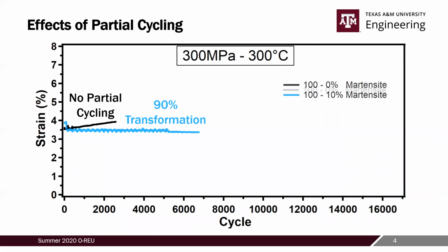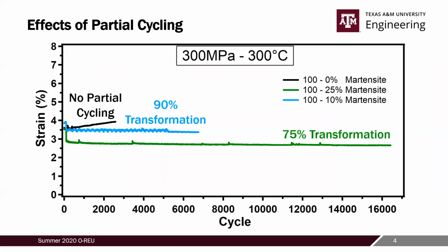So if we do a 90% partial transformation, we can extend the fatigue life to around 7,000 cycles. And with a 75% partial transformation, we can achieve over 16,000 cycles, which is over 5 times the fatigue life that we can get with no partial cycling.